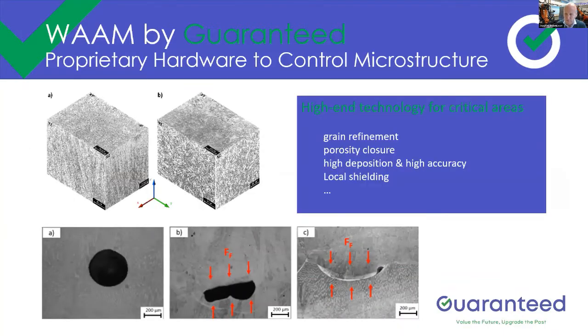As you know, additive manufacturing, especially for alloys like titanium or aluminium, can result in an elongated grain due to the solidification scheme of these types of materials. What we are currently doing is working in a European project on a way to actually lead to grain refinement directly on the as-deposited microstructure, so that we can avoid having to go through a thermal cycle after production, which of course leads again to significant cost savings for the end user.